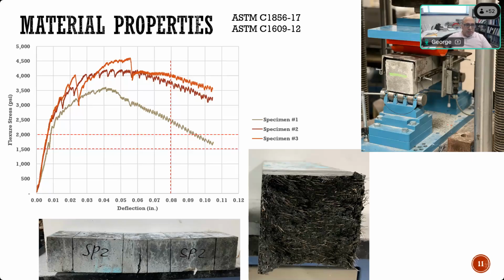So here are the flexural stresses and the deflection. And you can see here what exactly is happening. After it cracks at this point, it's still carrying load until it reaches a peak. And even after the peak, it still has some residual capacity. So it does not break. And that's the function of the fibers that are bridging the gap once a crack occurs.